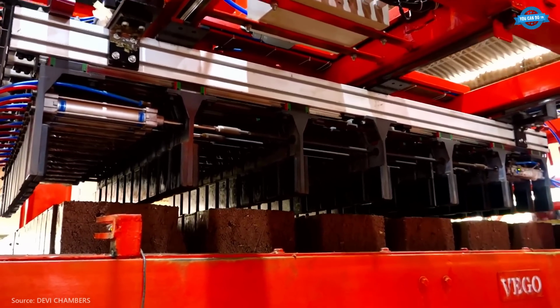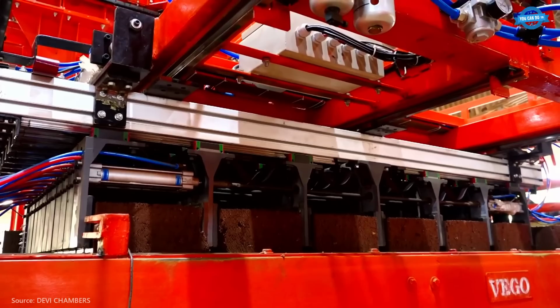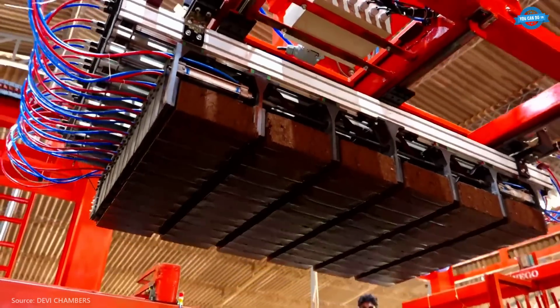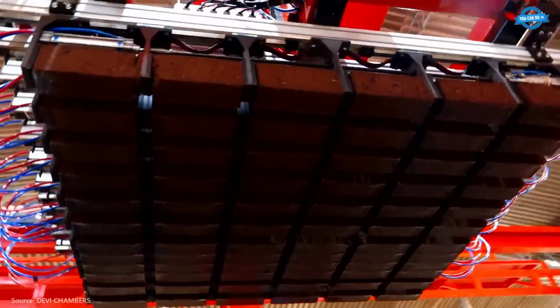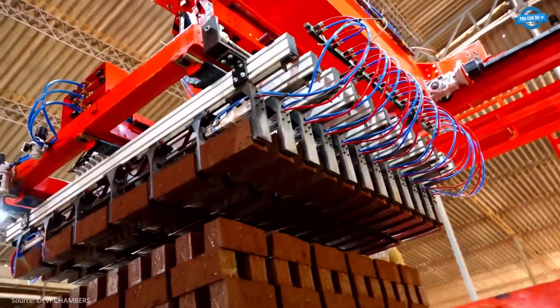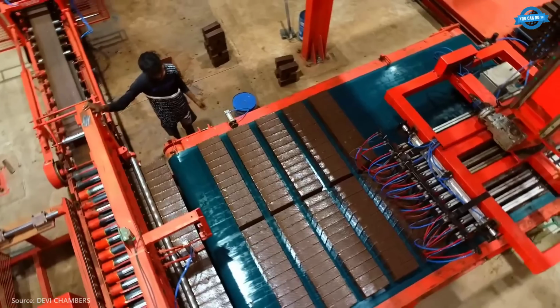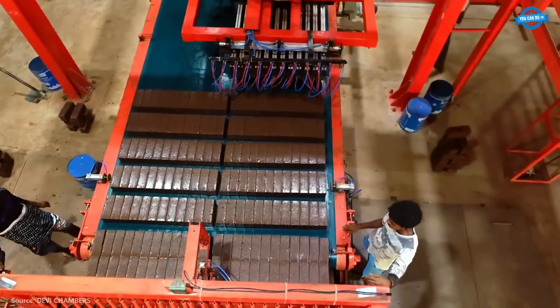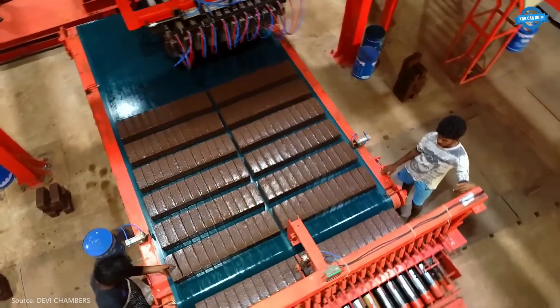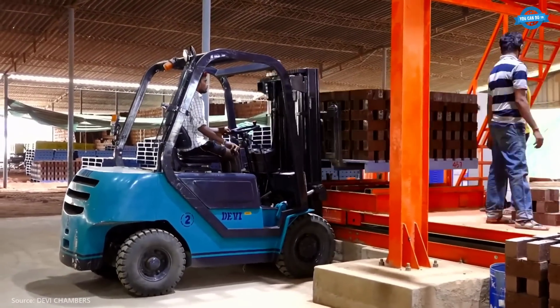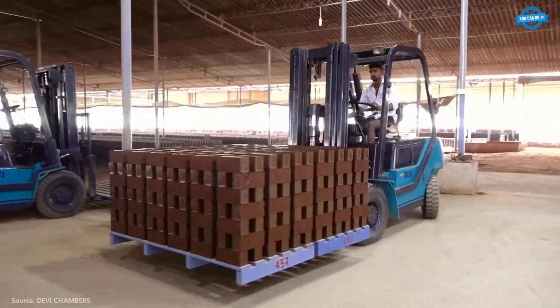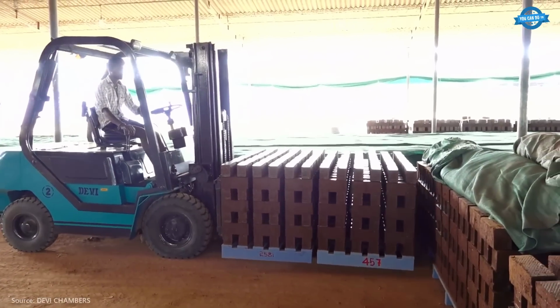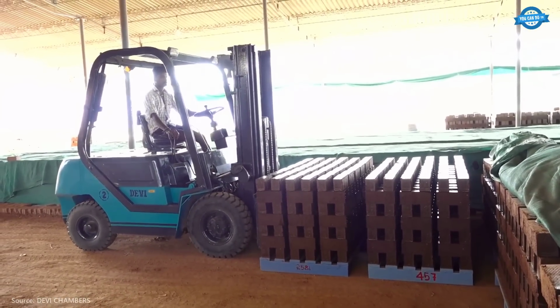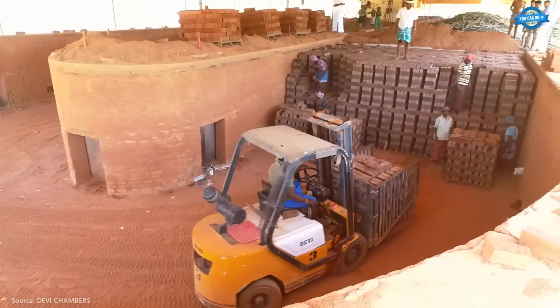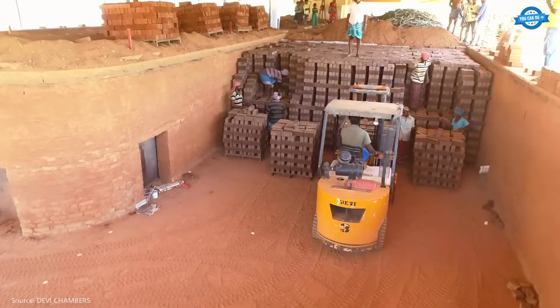Once cut, the bricks are stacked using robotic stackers onto pallets for drying. Initially, they are shade-dried before being transferred to open areas for further drying. Following this, the bricks are fired in kiln chambers at controlled temperatures for 40 to 50 hours. This critical firing step imparts the bricks with their characteristic color, density, and solidity. Proper firing ensures that the bricks produce a distinctive clay pot sound when struck, signifying their quality. Technological advancements enable the workshop to maintain high production volumes throughout the year, irrespective of climatic conditions.